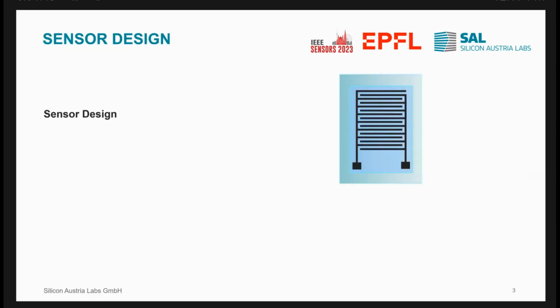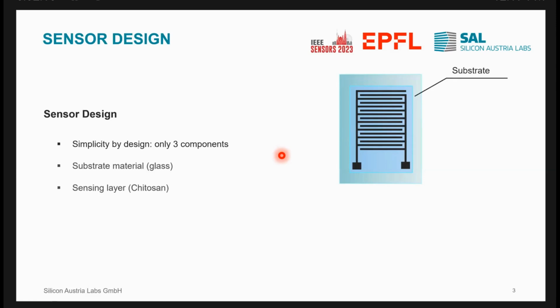So the sensor I will be presenting today is actually quite simple in design, which is an advantage as only very few materials are used. It consists of only 3 components. So you see here an interdigitated design, which is fabricated on a glass substrate. Then there's a sensing layer, which is in this case Chitosan. I will talk about this later on, what Chitosan is. And then the electrodes are fabricated from laser-induced graphene, which is derived from this Chitosan. So no additional material is added.